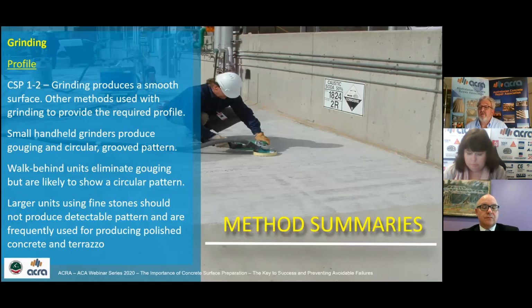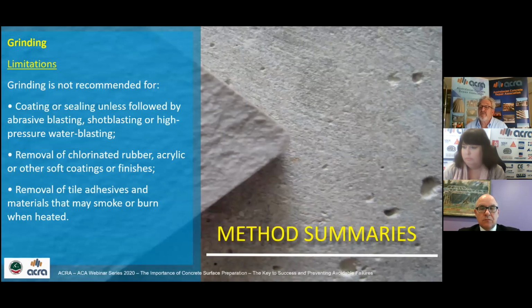Profile is CSP 1 or 2, so it's smooth. Generally, other methods can be used with grinding to get the profile. The small handheld grinders produce gouging, generally in a circular groove pattern. Walk-behind units eliminate the gouging. They can show a circular pattern, but the walk-behind ones are frequently used for polished concrete and terrazzo.